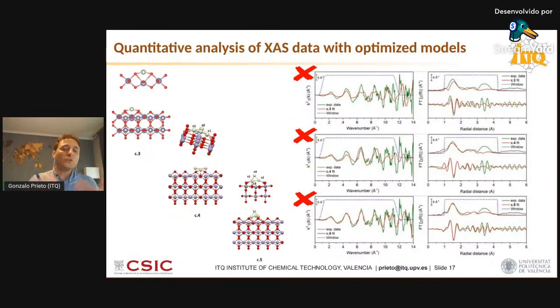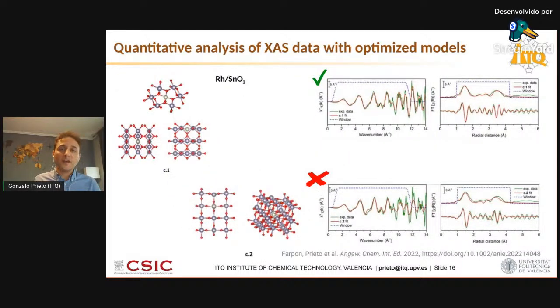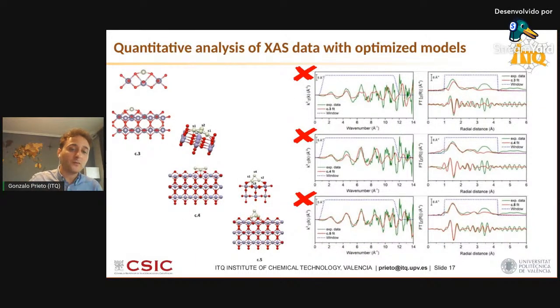And it is important to do this for quite a number of different site models, and to combine scattering paths from different models, just to check if perhaps a single rhodium atom substituted at a specific position on a specific facet of tin oxide does describe your experimental data, but the combination of that with a few low nuclearity clusters provides an even better fit, suggesting that you may have two populations of species. And this is already a warning for anyone doing catalysis, because once you have two different species, you need to figure out very carefully which one is responsible for catalysis.